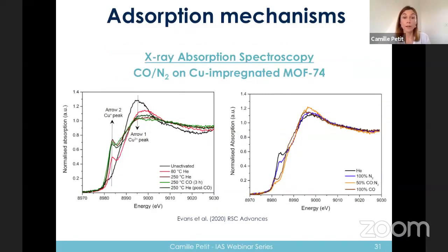If we take, for instance, another technique, which is X-ray absorption spectroscopy. So here we're monitoring the chemical nature, or the chemical environment of atoms. So we take here the example of a CO uptake on a copper impregnated MOF, which is MOF 74. And we wanted to know first what was the nature of the copper atoms within the MOF 74. And if you look at the graph on the left here, you see a decrease of the copper 2+ peak upon activation. So those lines here correspond to different types of activation. And so you see that you're decreasing your amount of copper 2+ and increasing here your amount of copper 1+, which is the desired form if you want to have preferential interactions with CO for the adsorption.